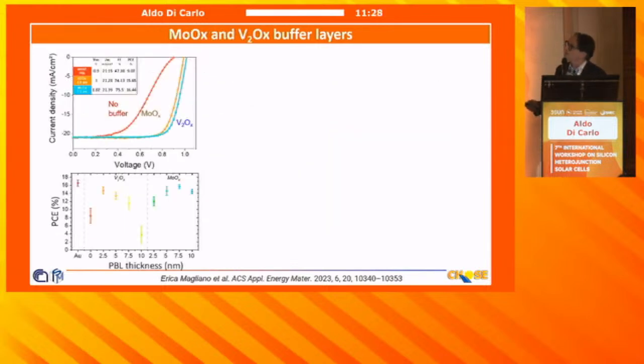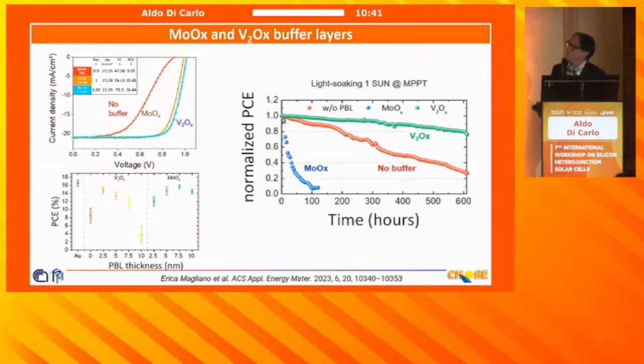The first one is to use molybdenum oxide, which is quite conventional, but also vanadium pentoxide as a buffer layer. We use these two materials, and you can see that without a buffer layer, with sputtering, you have an S shape, which is damage to the layers. But when you use molybdenum oxide or vanadium pentoxide, you resemble the conventional IV characteristic. The efficiency with these two materials is also quite aligned with the opaque thermally evaporated electrode. You can get almost the same efficiency with both vanadium and molybdenum oxide. However, there is a big difference between the two.